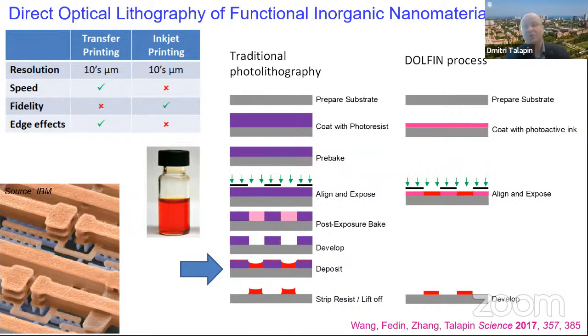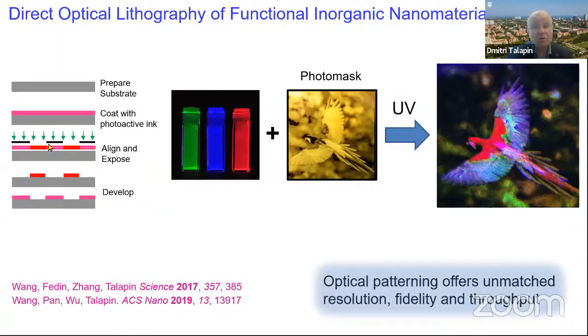To address these challenges, we developed a cousin to traditional photolithography that we call DOLFIN. The idea is to avoid using photopolymers, photoresists, but instead to design the surface chemistry of nanoparticles to act as the photoresist. So we can coat a layer of quantum dots and then expose them, and then, depending on how we design the chemistry, exposed or unexposed regions will allow us to be removed selectively.